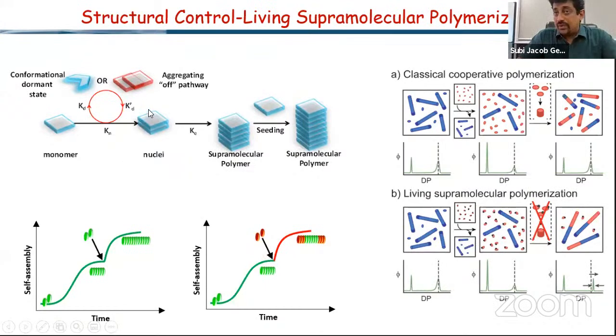We know that nucleus formation is an energetically unfavorable process, but in most synthetic supramolecular polymeric systems, the activation energy for this step is not so high. As a result, most of them undergo spontaneous nucleation. So if you add another batch of monomer into the system, nucleation happens immediately, and that will kill all structural control in your system, right? If the additional monomers start growing on the existing chain, we can control the dispersity or the molecular weight. But if they start their own nucleation centers, they start their own chain formation, and you lose that structural control in the system.